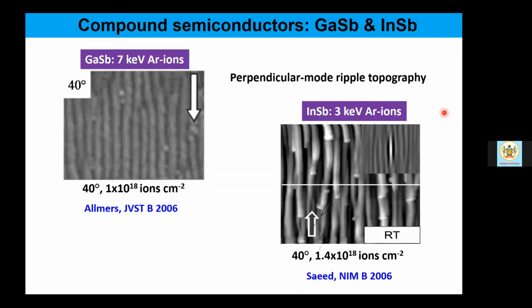But the moment we get into oblique incident ions, argon ions only, but with a little higher energy up to 7 kilo electron volt, and incident at an angle of incidence of 40 degree, we get to see this kind of ripple patterns, pretty well ordered. And these small bamboo stick kind of patterns arise in the case of indium antimonide.